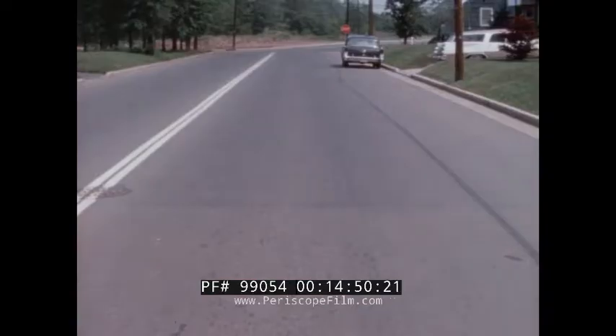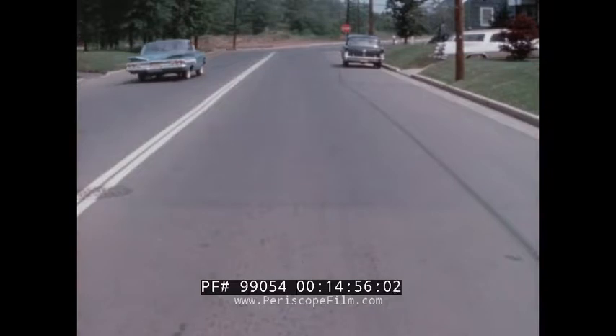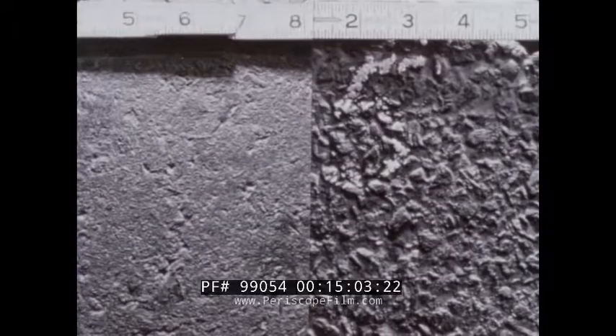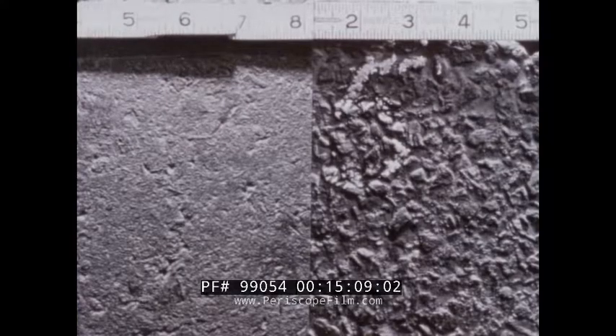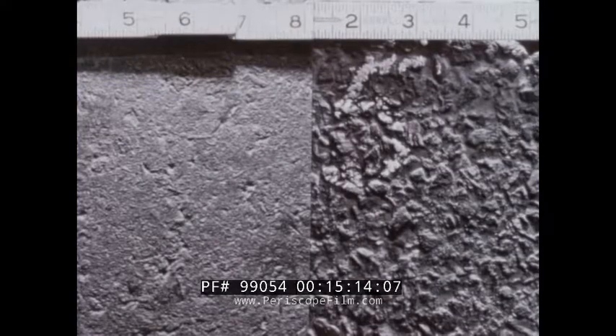And since the experiment at the Jeffrey mine, many field tests have been conducted with the cooperation of various highway authorities, and they bear out the laboratory observations. Here, for example, is a test strip in Manville, New Jersey. It was constructed in 1959. An adjacent and comparable standard asphalt pavement was placed simultaneously. On the right is the standard pavement after only 3 years of service. The raveling is clearly visible. On the left is the asbestos asphalt surface.